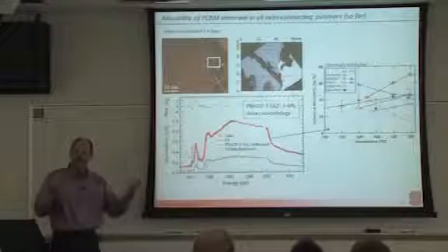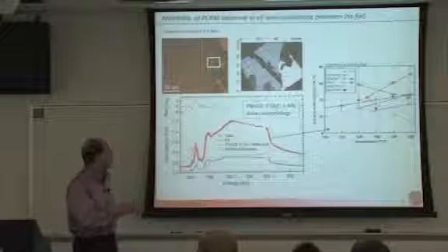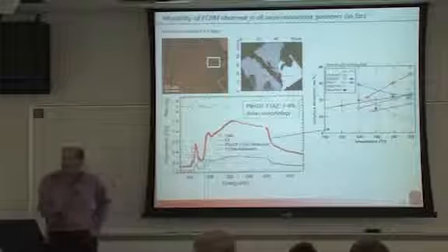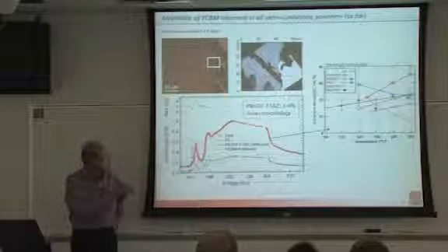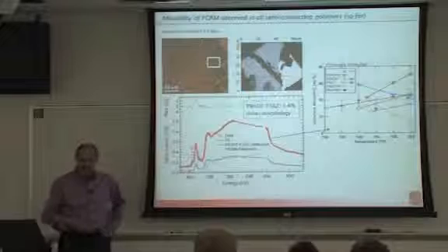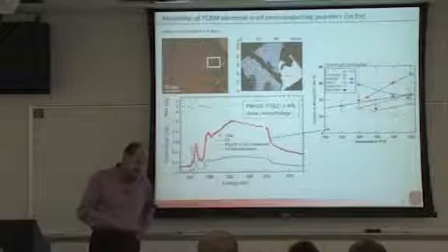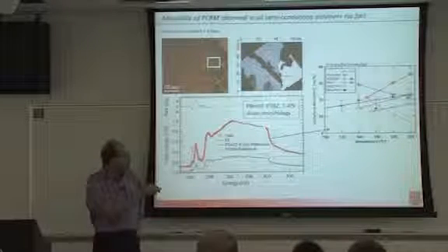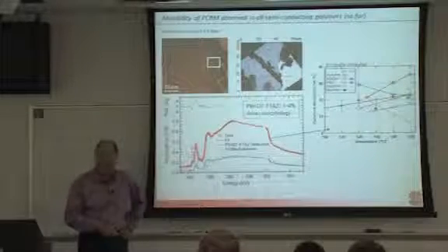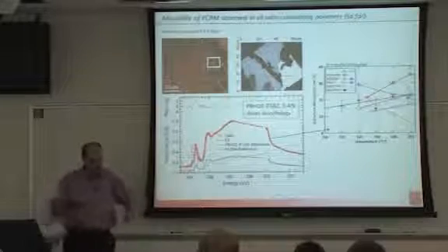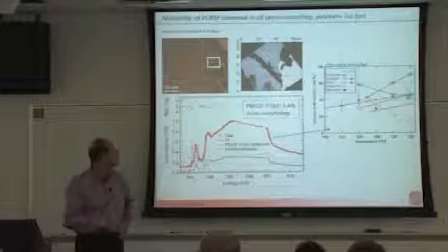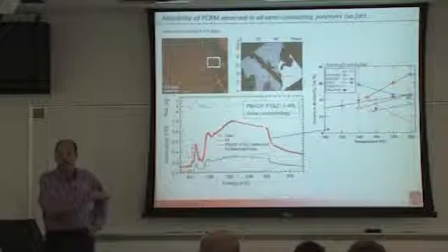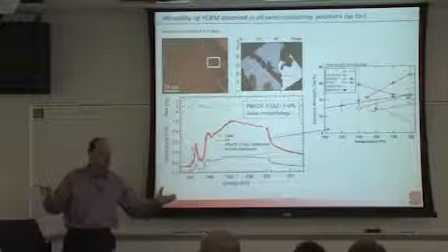So then we sort of went further and did this for a number of other systems, and you see that we basically find that, yes, PCBM is, these are again just, I should always put the miscibility here in quotes, because that's the phenomenological measured quantity, but they are on the order of 10, 20, 30%, so they can be quite high. And what we find is if it's extremely high in one case, then the performance, of course, suffers. But all of these devices work to some degree. And so what's the role of this?